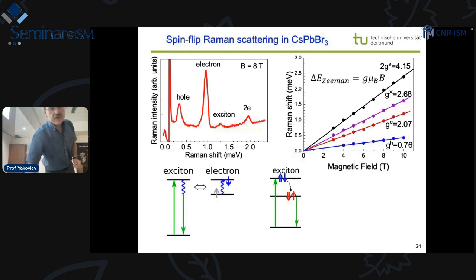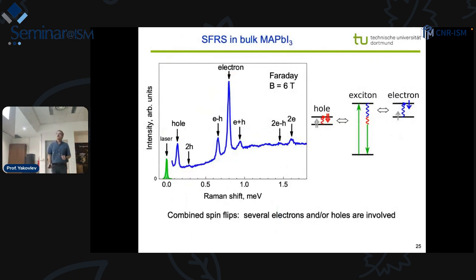Kind of a surprise for perovskites was also that we observe not only the single spin of the electron or the hole, but we observe also the multiple spins. For example, the two-electron spin, or electron plus hole, electron minus hole. It means that the exciton, when it's photo-generated, interacts not only with one resident carrier, for example, electron. It has also, in its orbit, or at least a tail of its orbit, hole spins. So the two carriers have a chance to make a flip.